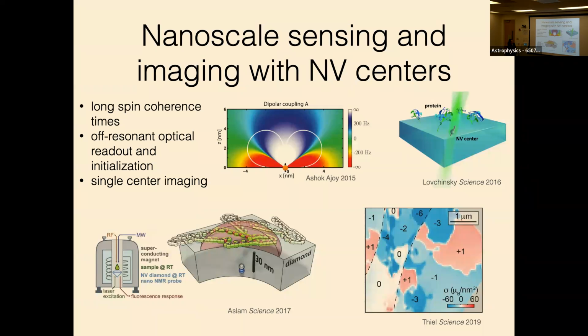So there's been a lot of activity in trying to deploy NV centers as sensors, for example, by decorating the diamond surface with molecules and trying to do nanoscale NMR. There's even been some developments over the last half decade where there are new pulse sequences where you can push this all the way down to being able to do chemical shift level resolution NMR. And then there's quite a robust community using NV centers to study condensed matter systems and materials, with this beautiful example from Patrick Maletinsky's group from a couple of years ago, where they uncovered new mechanisms for magnetism in chromium triiodide, which is one of these 2D materials.